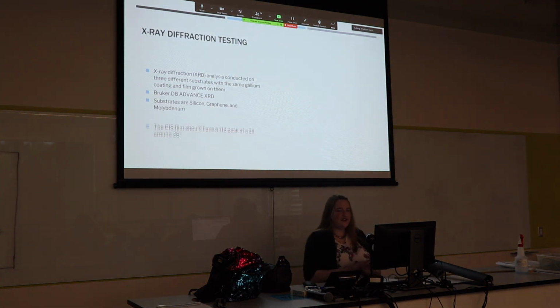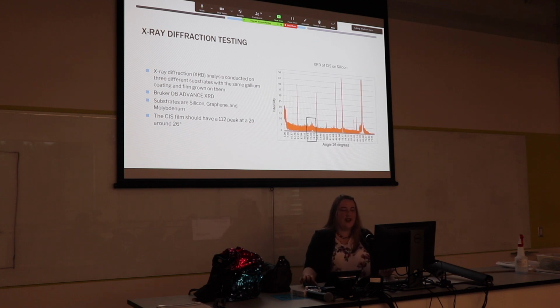Next, we took it up to the geology lab and used their Bruker D8 Advanced XRD, which is the X-ray diffraction analysis machine. We did try it on a couple different substrates, not just the silicon. We also used sheets of graphene that were layered on top of each other that were almost like graphite, and molybdenum. And we are looking for this peak right here at a 2 theta of about 26 degrees. We can see a very small peak, which is fine. It's not that intense, but it's there. And that is our 112 peak for our film.